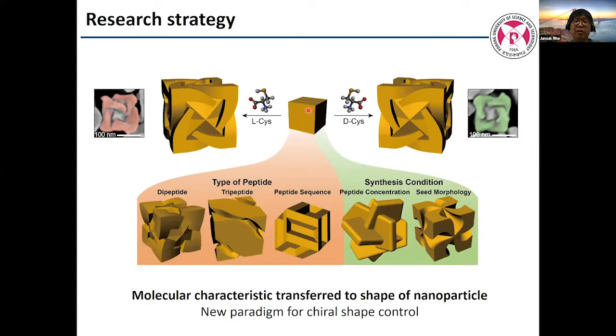So this is gold nanoparticle growth in the normal, inorganic case, and we added this organic amino acid. They have left-handed and right-handed forms, and during the gold nanoparticle synthesis we added this, and magically the left-handed chiral nanoparticle and right-handed chiral nanoparticle, exactly mirror images, were made. So the organic chirality is transferred to the inorganic growth. After we found this scheme, it became very easy. So we tried a lot of different concentrations, temperatures, growing conditions, different peptides, different proteins, and so on.